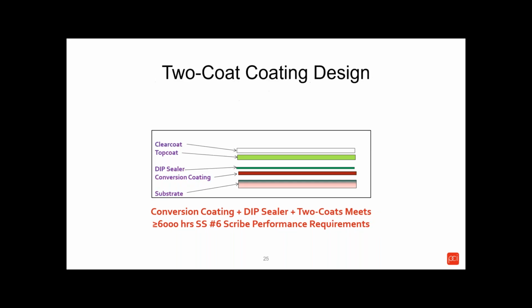Okay, number six rating. Then we looked at the two-coat process, mainly because two coats gave them some appearance options they didn't previously have, and we'll talk about that as we get to another slide. So we looked at what the performance of a two-coat process is. Again, the same substrate used, aluminum in this case, a conversion coating on that aluminum, and a dried-in-place sealer to improve adhesion and corrosion protection, mainly used to promote adhesion on stainless steel. A top coat was applied to give it its basic appearance, and a clear coat was applied on top of the top coat to improve the mechanical performance of that top coat. So things like chrome lookalikes, we'll see how that works here. This package actually provides well over 6,000 hour salt spray protection. The only difference, again, is adding an additional coating of powder.